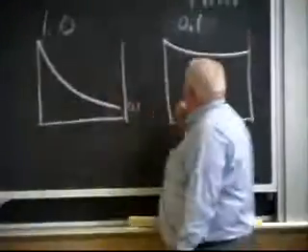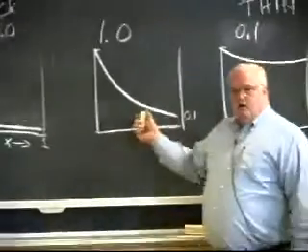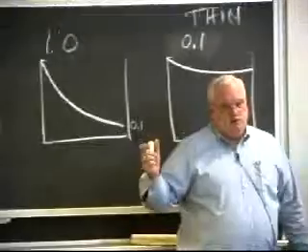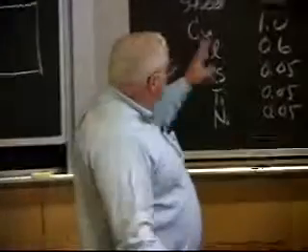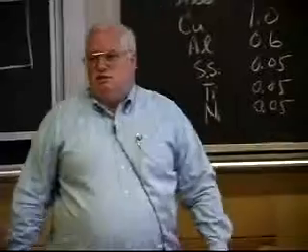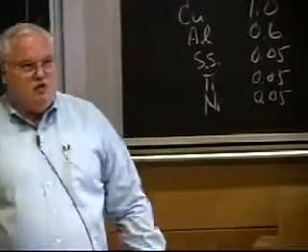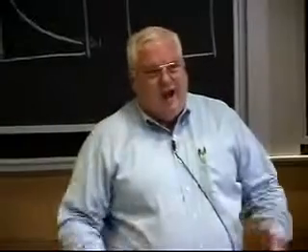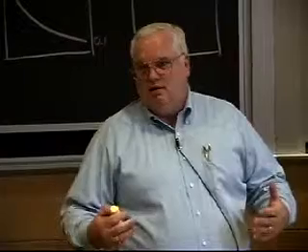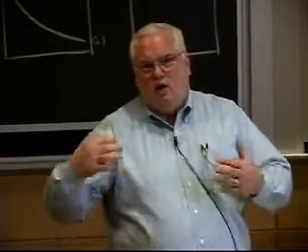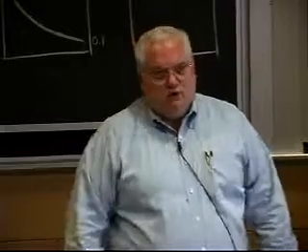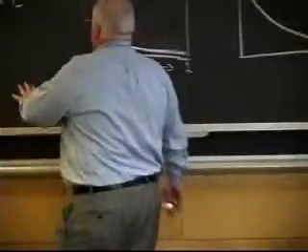Essentially very thick, very thin, or somewhere in between in the transition region. And so now, rather than solving Fourier's second law of heat conduction for any thermal problem, I can estimate the size of a heat affected zone or the amount of cooling that occurs in the process. And actually about 2 or 3 of your homework problems ask you to either do this for the Fourier number or the Biot number,